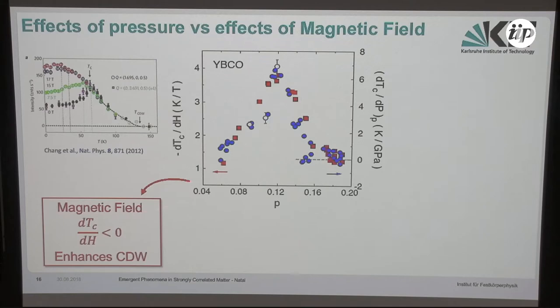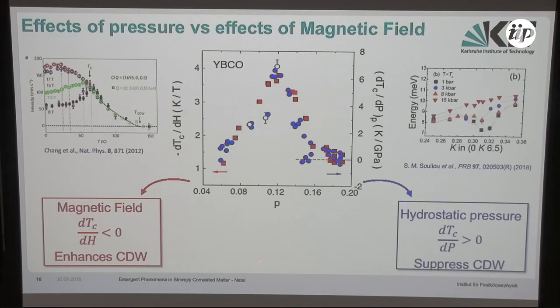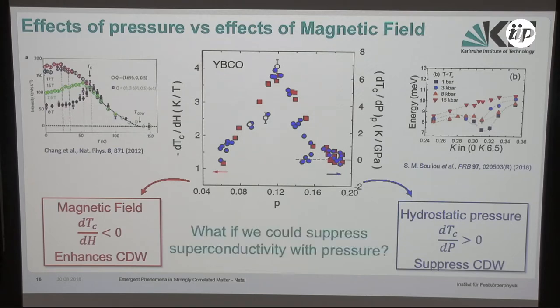I'm not going to spend more time on the hydrostatic pressure because in the end, what I'm just saying is that, well, if you apply a magnetic field to suppress superconductivity, you enhance the charge density wave. And if you use pressure, well, you increase superconductivity and you suppress the charge density wave. Okay, so maybe a bit faster than what you had expected, but in the end, it's not such a surprising result. Now, the question we ask ourselves: what if we could suppress superconductivity with pressure? And so how do we do that?